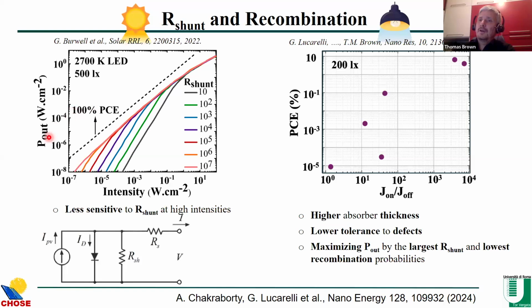Here, there's a plot of the output power versus intensity for different shunt resistances. So at high intensities, so those found outdoors, the effect of the shunt resistance isn't very great. At very high intensities, if you have a shunt resistance which even changes by orders of magnitude, you see no effect. Whereas at low intensities, the effect of the shunt resistance is huge. So to develop efficient photovoltaic cells for indoors, one needs to be very careful to have very high shunt resistance and minimize recombinations.